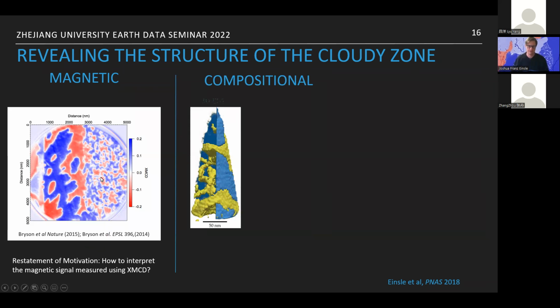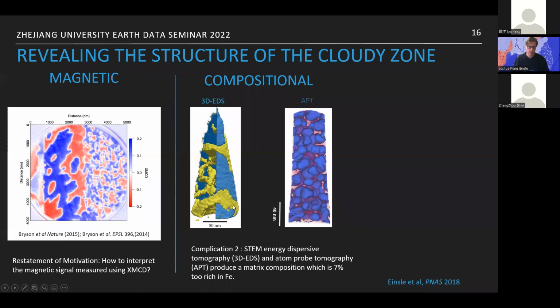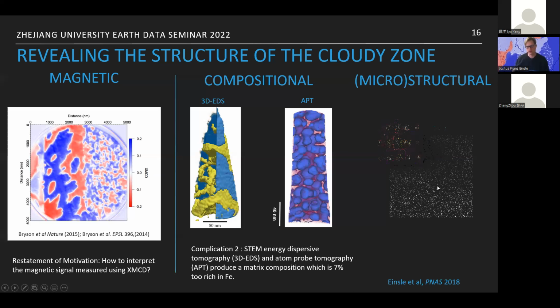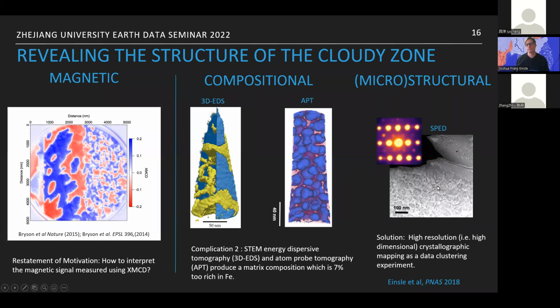But we now have very good compositional confidence that our tomography and our atom probe quantifications present something where the matrix is 7% too rich in iron. So what we've done now is decided to explore the crystallography. Is there something that we're not expecting in the matrix? And in this case, we use data clustering to try and identify what the two phases are.